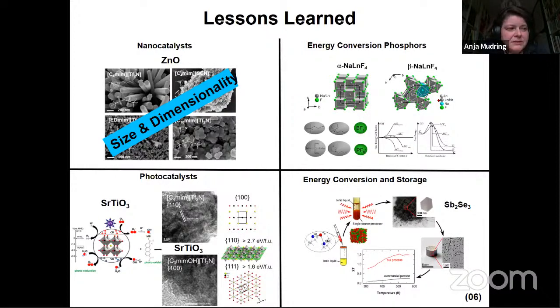A big class of materials that can efficiently split water and also decompose organics in wastewater are, for example, the simple perovskites. Interestingly, when you look at the performance of the different surface facets of such a perovskite, you see that the different crystallographic facets have different efficiency with respect to water splitting, hydrogen generation, or when you imagine a large organic molecule that needs to attach to the surface and then gets degraded. So depending on the application, although you're using the same material, it's desirable to have different surface facets exposed.